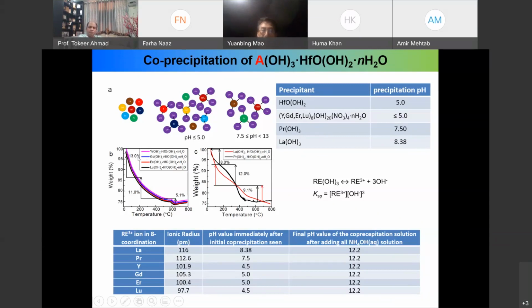So that's why for the precipitant here, with this general formula, for these 4 elements, we see from the TGA a very smooth decrease of the weight. But for these 2 A-site elements, there are 2 regions for the weight loss. So that's consistent with these two elements. Actually, the precipitate is not a uniform process. So that's one thing I want to mention.